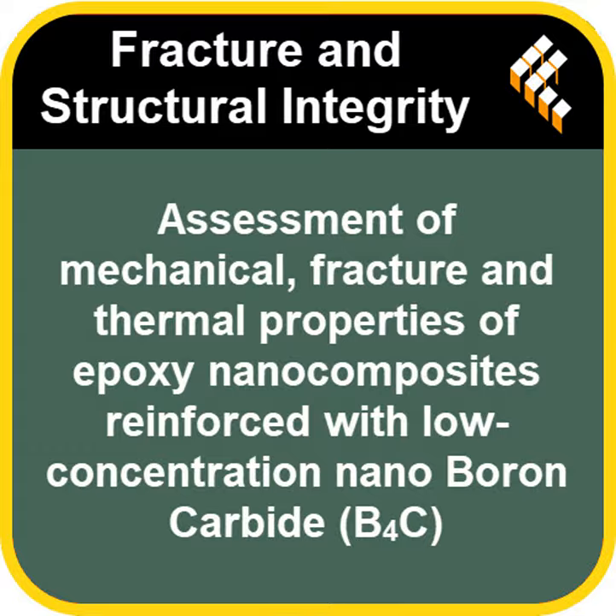Looking at fracture toughness, KIC, measured with specific crack tests. Here, the trend was different again. It improved steadily across all concentrations. The biggest improvement was right at the top, 0.4 weight%, delivering that near 70% enhancement you mentioned earlier. 2.97 MPa√m compared to 1.75 for the pure epoxy.